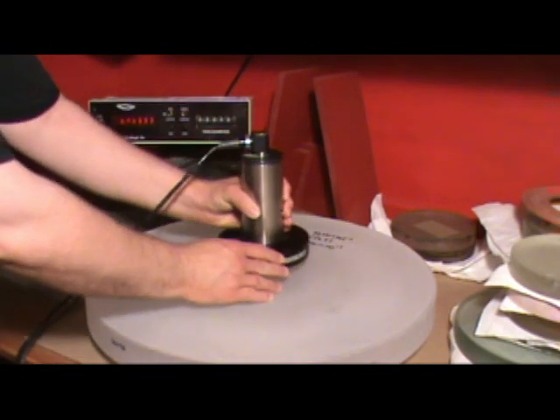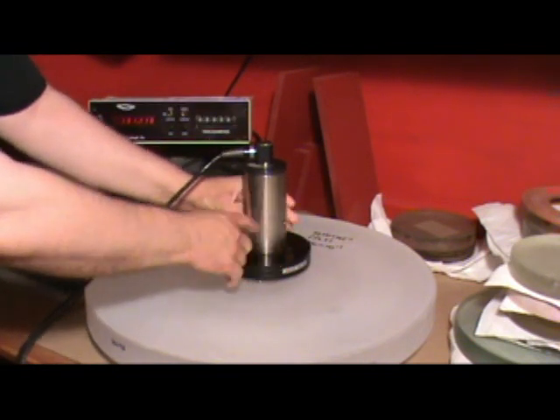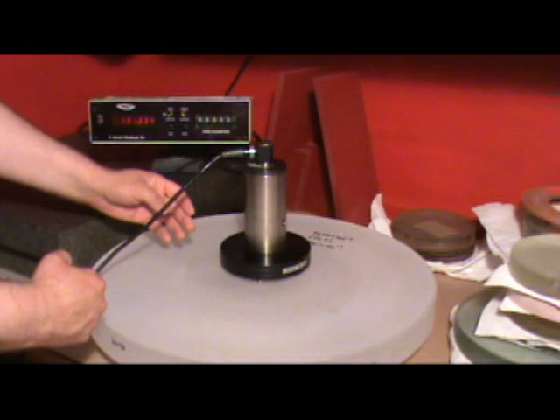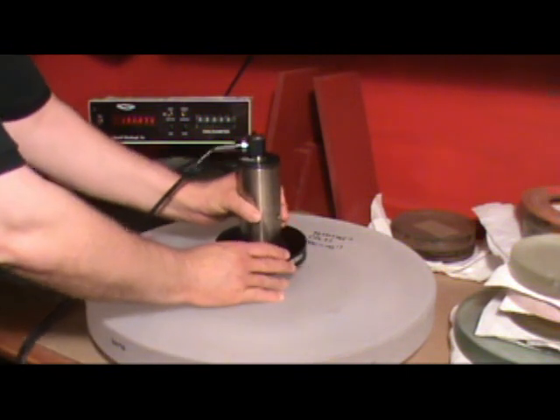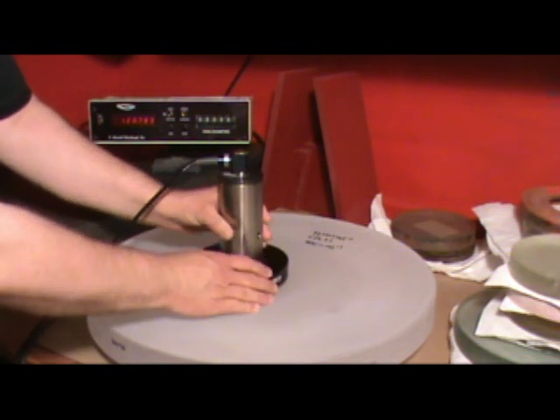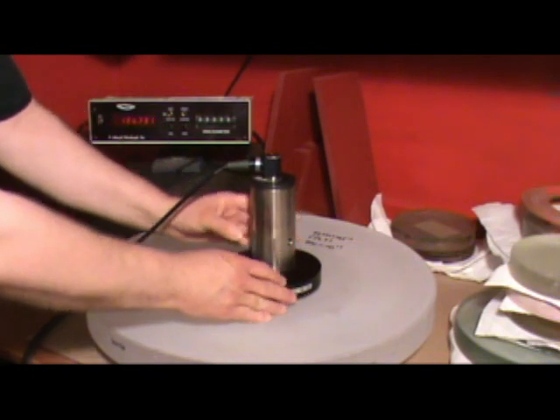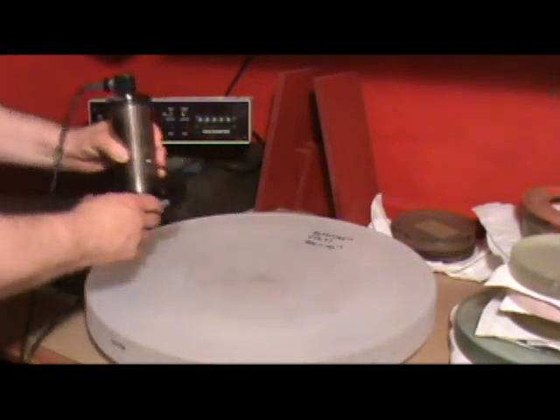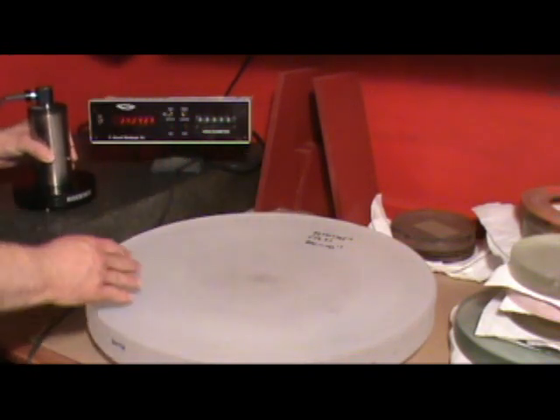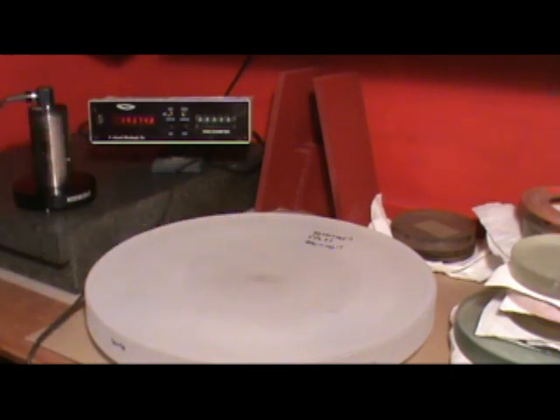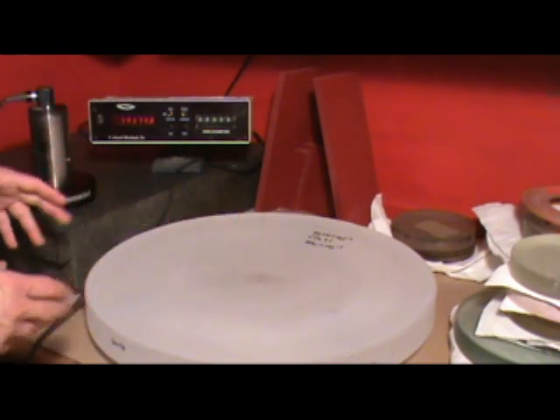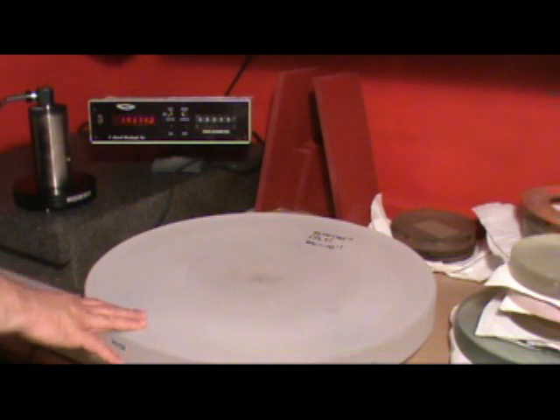So what I actually do is make a set of three or four measurements in each one of those three areas. I'll make a measurement, move it over a little bit, make another measurement, move it to a slightly different spot, and so on. And then I take the average of those sets of measurements so that I can get a little better picture of the actual shape of the mirror.